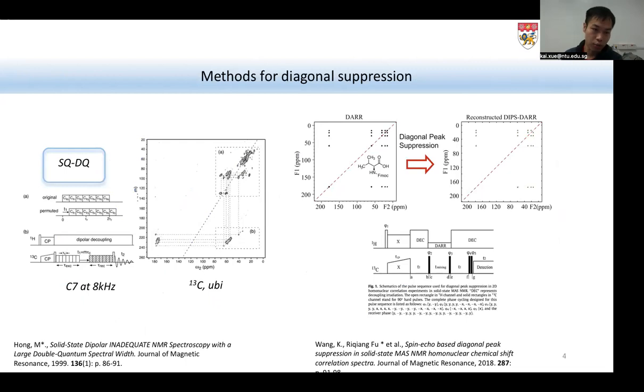To solve these problems, people sometimes use single quantum and double quantum spectra. With a good dispersion in the double quantum dimension, we may resolve the peak overlap. But the problem for single quantum double quantum spectra is the efficiency of double quantum excitation for these scalar or dipolar coupled spins. The efficiency to excite this double quantum coherence decreases if the distance between the spins is far. And our interest is actually long-range contacts.